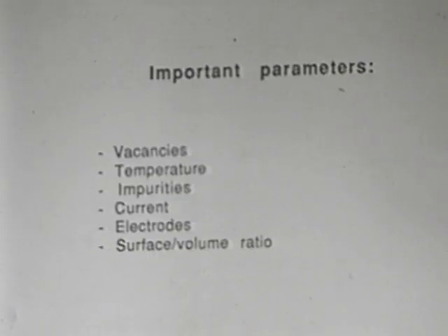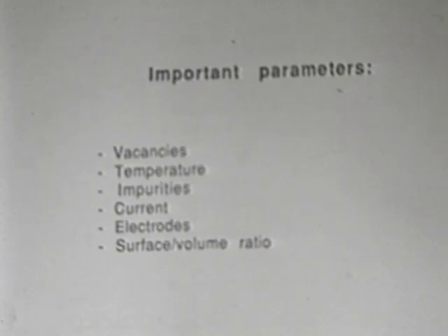The amount of vacancies is very important. I mean, if there are no vacancies, there's no deuterium. But there is a limit of stability of the crystal. If you put too many vacancies, the crystal will be destroyed. So this is an important factor. We don't know exactly what number of vacancies we have. These crystals have not been manufactured for vacancies. They were manufactured not to have vacancies. So we have very little amount of vacancies in our crystals.